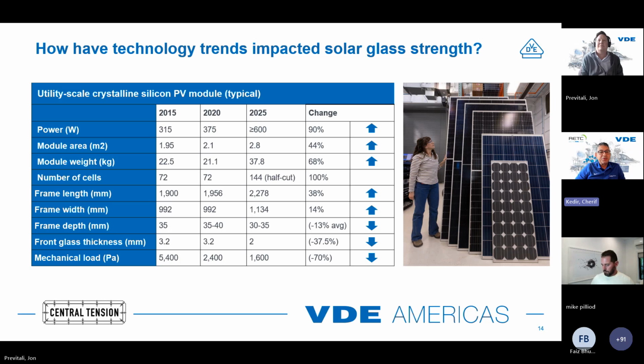Historically, everybody thinks of modules as having been very resilient in the past, and it's absolutely true. Back in the days, glass on modules was usually 4 millimeters, and it got thinned down to 3.2 millimeters, and the industry freaked out about that trend. The frames used to be 50 millimeters thick. They were really, really heavy duty modules. These issues didn't happen. They weren't reported.